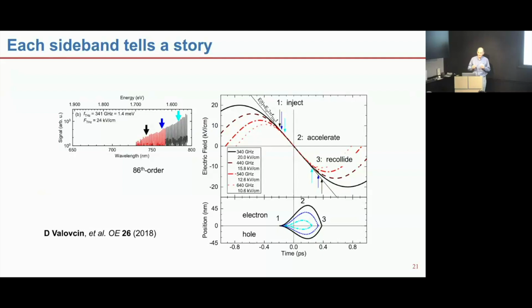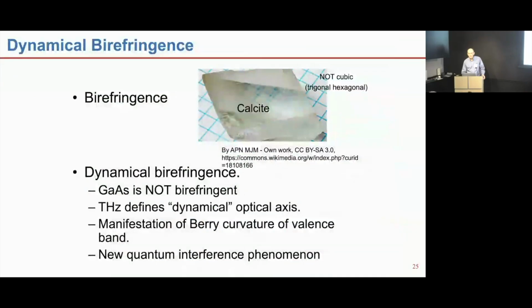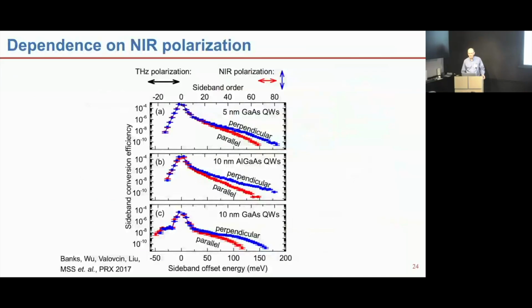Couldn't it just be that the scattering off impurities is much stronger than the scattering off LO phonons? I doubt it, in the sense that what I remember is that in gallium arsenide, the LO phonon scattering is the showstopper. But yeah, we were honestly surprised. Initially we didn't see sidebands above the LO phonon energy, and then we did, and we wondered why.